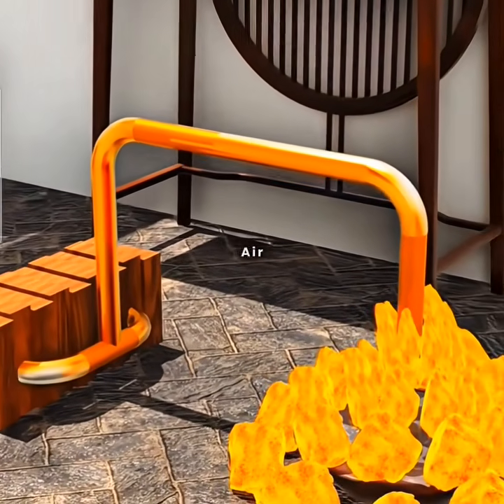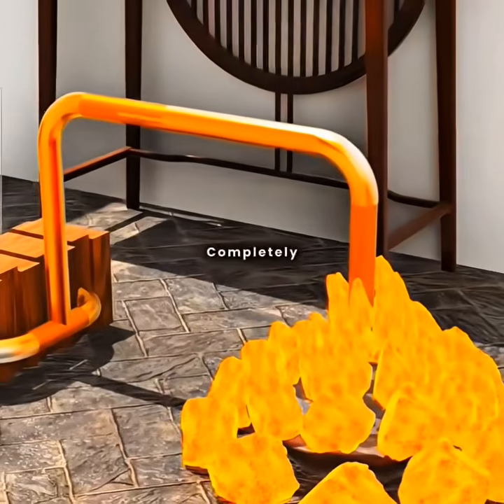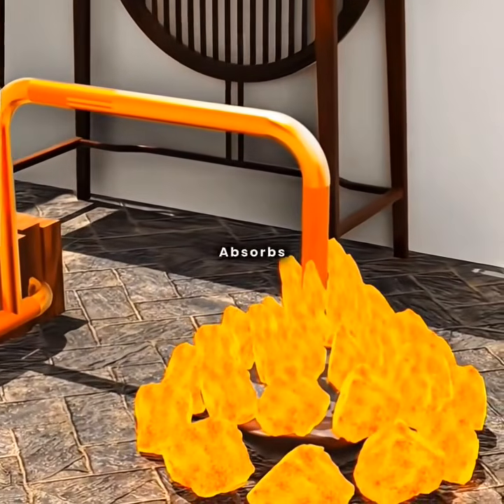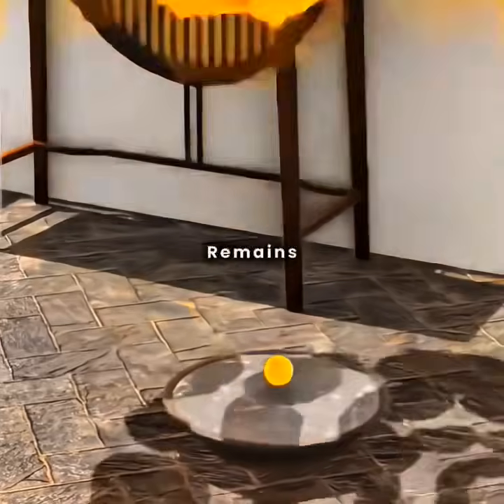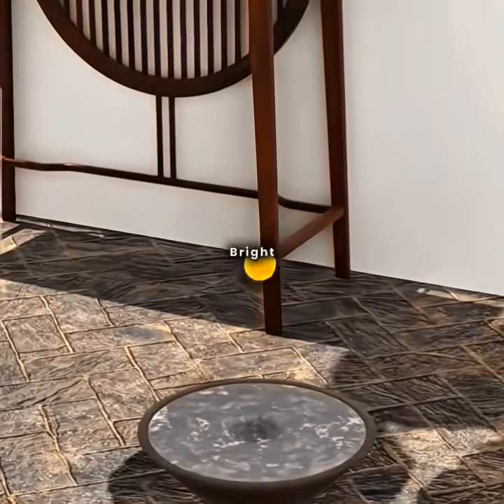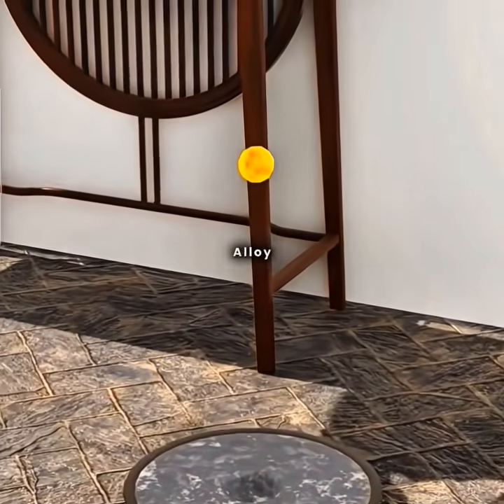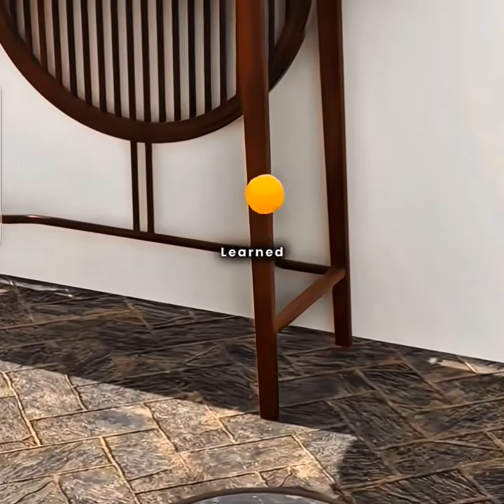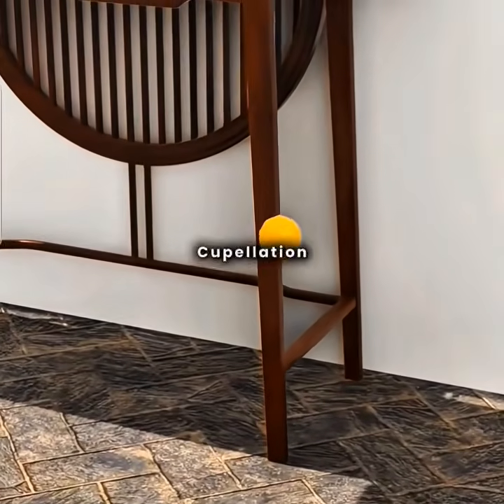You continue blowing air at high temperature until the lead is completely blown out, and the bone ash no longer absorbs lead oxide. At this point, what remains on the ash bed is a glowing, bright, high-purity gold-silver alloy. Congratulations! You've now learned the ancient gold refining technique known as the cupellation method.